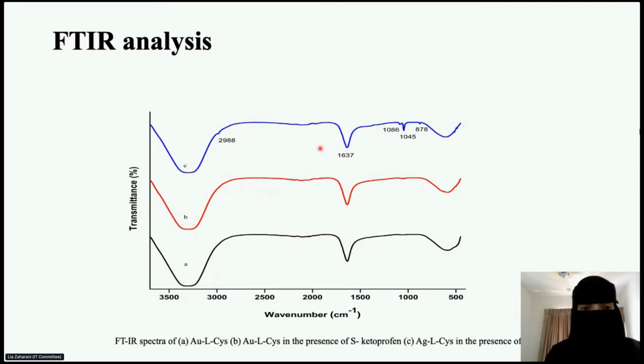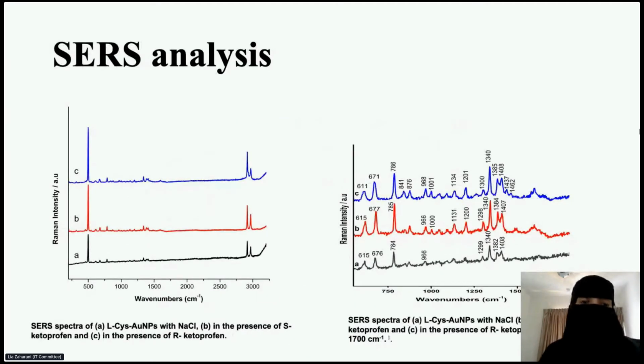However, when we introduce R-Ketoprofen, we got new peaks at 2988, corresponding to the CH stretching, and this one is the same with slight shifting, and we got this peak corresponding to the CH3 stretching, and this one corresponds to the ester CO stretching, and this peak corresponds to the CH3 rocking and COH in-plane bending. This new peak confirmed the interaction between L-Cysteine and R-Ketoprofen, and also confirmed the selective response toward only R-Ketoprofen. After the FTIR analysis, I did Raman analysis.